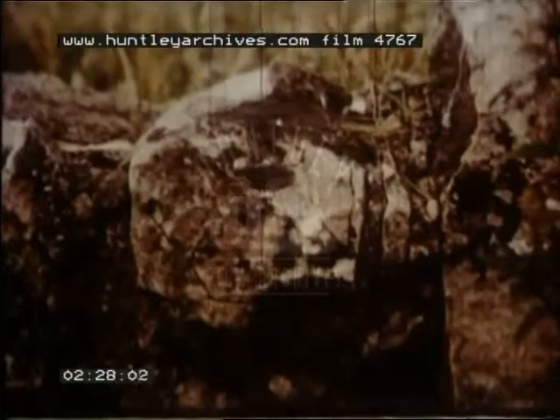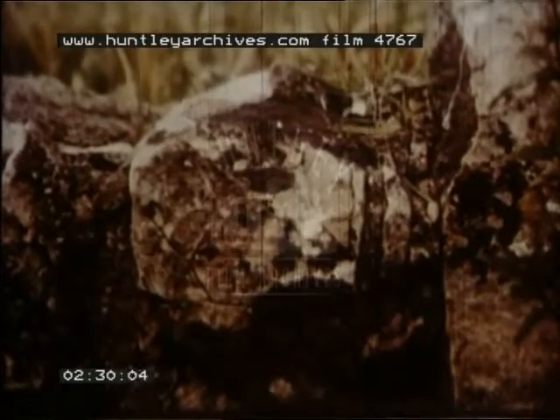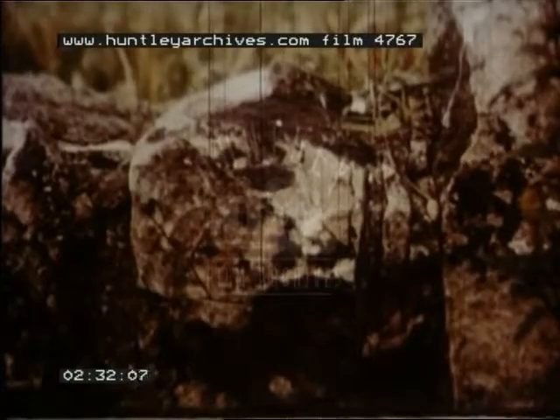Frost damage is not a major cause of decay, except in those instances where the stone can become frozen while very wet. Frost can, however, dislodge pieces of stone that have been loosened by other means. Although there are many destructive permutations, including organic growths, which may play a minor role, it is true to say that water is involved in almost every form of decay.